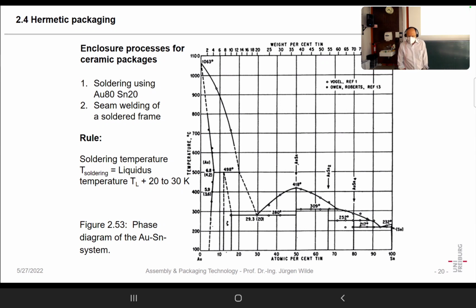No, there are two reasons. One is it's not high enough, the melting point, because here we want to have such a melting point around 300 degrees centigrade. The second reason is there are other alloying elements which we can put in, which have the same effect. For instance, we can put in silver, and silver is significantly cheaper than gold is. So taking tin silver, for instance, we will later on see it, or even we can use tin copper or tin silver copper, would have the same effect and same melting point. And in that way, yes, we take advantage of that point.